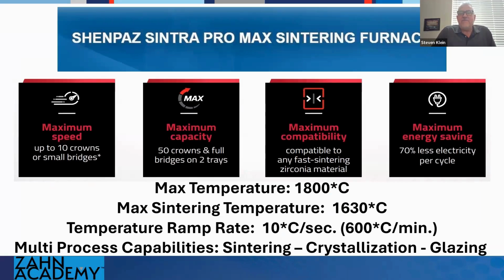Some of the quick features: it does have a maximum temperature of 1800 C. Maximum sintering temperature is 1630, but that's the long program, 1630. I know that's written a little confusing, but the maximum temperature is actually 1800. Single units, quick up, down, very fast. And so it has a lot of capacity for potentially future materials that require even higher temperatures. Ramp rate, a blistering 600 C per minute. It's really fast at 10 degrees per second. And for a larger chamber, this is really unique. It's not something you see on any other furnace. I haven't seen it anywhere else yet like this.